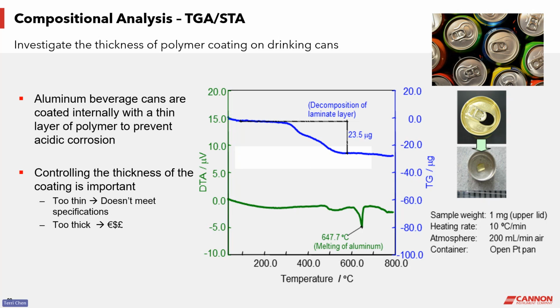A TGA analysis can help you to quantify the thickness of a can coating, how thick your competitor coat their cans. To find out the answer, we can cut a piece of can and load it to a TGA or STA instrument and conduct a simple temperature scan measurement. At temperature greater than 400 degrees C, we observed a small percentage of weight loss, which correlates to the decomposition of the polymer coating. So using the mass of the polymer and the can surface area, we can then calculate and estimate the thickness of the coating.